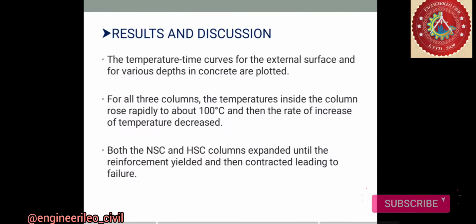Now we are going to see the results and the discussion part. The temperature time curves for the external surface and for various depths in concrete are plotted. For all 3 columns, the temperatures inside the column rose rapidly to about 100 degrees centigrade, and then the rate of increase of temperature decreased. And it can be seen that deformation in the high strength columns was slightly less than for the normal strength column. Initially, deformation of the column was mainly due to thermal expansion of concrete and steel, while the effect of load and thermal expansion is significant in the intermediate stages. The effect of creep became pronounced in the earlier stage due to high fire temperature. For high strength concrete columns 1 and 2, it is 225 and 189 minutes respectively.